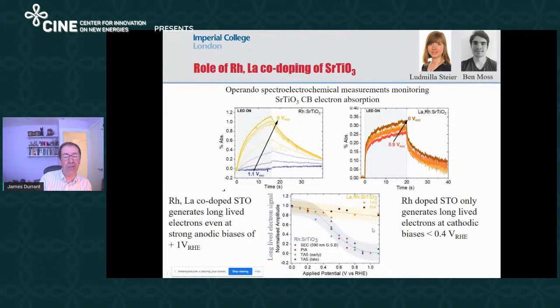And the essence is that co-doping with lanthanum makes it much easier to generate the long-lived electrons, which in this case are going to be driving protons to molecular hydrogen. And so here's some optical data where we're looking on the seconds time scale now, LED on, then light off, and you can see the accumulation of electrons in the strontium titanate as a function of applied potential. And what you can see is you have to apply a potential near zero versus RHE, so quite a cathodic potential, to get a lot of long-lived electrons accumulating in the strontium titanate. But rather in contrast, when you lanthanum dope it, you can apply a potential of plus 0.9 volts and still have lots of long-lived electrons.